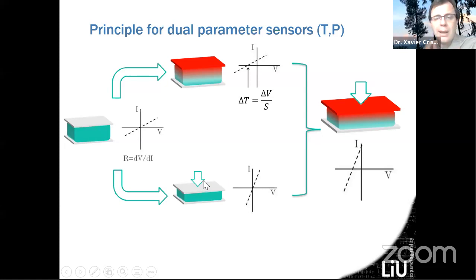Now, looking at temperature, if you apply a temperature gradient between the top and bottom electrode, what is happening is that you are going to shift the IV curve by a potential, which is the Seebeck potential, the thermoelectric potential. So a temperature gradient applied will be seen as a shift in the curve here.